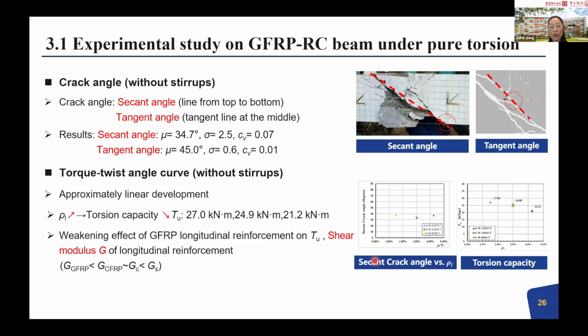We also found an interesting phenomenon. For torsional behavior, although we do not have a stirrup, maybe the longitudinal bar will contribute to torsional behavior. But we found that if we increase the longitudinal bar ratio or the longitudinal bar area, there is a very clear tendency of reducing the torsional capacity. This is not the same as what we found in steel RC beams.